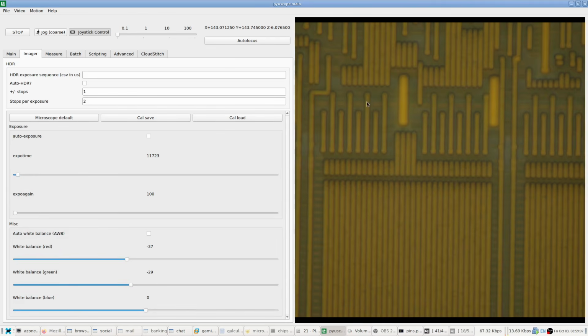But it is interesting that this looks a lot more like an older process where typically on the non-planarized 800 nanometer or 1 micron and up scale nodes, it was very common to see big annular rings on the ends of traces, and you could even often see a little bit of a divot in the center where the actual via was. And so it doesn't look like there's an obvious depression where the vias are. There's maybe a tiny little dot, but not too significant. But the wider area does give us a good indication that, for example, right here, there's probably vias. And these traces here, not seeing any vias in them at all, are likely dummy fill.